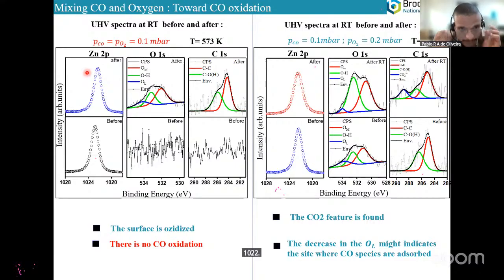1022.4 is expected. And the oxygen atoms reveal to us three new components. This is the oxygen bound to metal, this oxygen bound to water, and this is the oxygen that makes a dative bond according to the literature results, which means an oxygen that belongs to the lattice. That's why I call this OL, but it's also surrounded by other water atoms and the environment atoms.